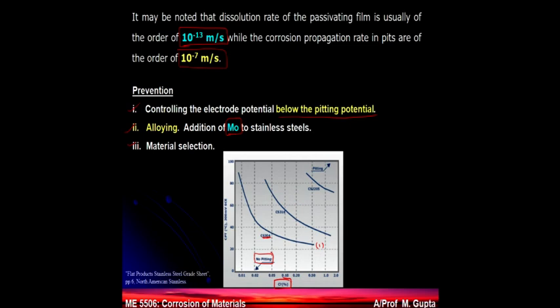So we can switch from 304 stainless steel to 316 stainless steel. Now this window where there will not be any pitting corrosion is increased by this magnitude. That means we can operate our material at higher temperature and higher chlorine concentration. And if we go to another more specialized steel, say CS2205, then we have a very big window below which pitting will not take place.